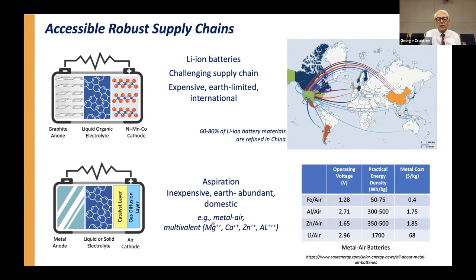For example, metal air batteries or multivalent batteries with magnesium, calcium, zinc, aluminum, 2 or 3 electrons per ion. You get 2 or 3 times the energy density in principle from that. So here, interesting graph or table, iron air, aluminum air, zinc air, lithium air. They're all candidates. You can look at the operating voltage. That's interesting. Here's the practical energy density. And for iron air, it's rather low. For lithium ion, practical energy density might be about 300 watt hours per kilogram. So you see aluminum is higher, zinc is higher. Lithium air is really high. It's a significant fraction of fossil fuel. And here's the cost. And it's pretty low for iron, as you might expect, pretty high for lithium, just because lithium is expensive. But these are things that we need to think about.